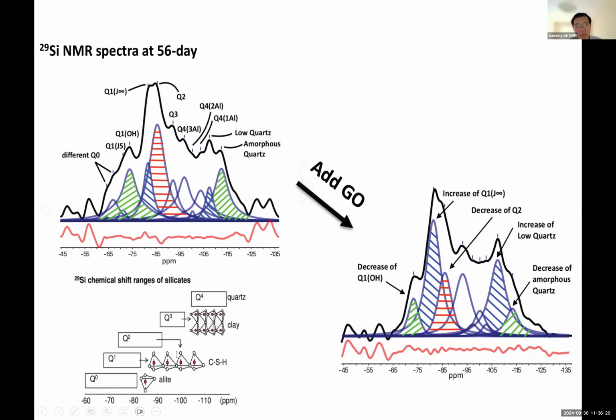But once they have more network structure, more neighbors being silicon or silicate, then you're moving into the domain of Q3, Q4. I would argue that when you have more than 50% Q3, Q4, then it's truly a polymer or geopolymer, instead of a linear polymer, which is a CSH gel or calcium silicate hydrate. I know the cement chemistry is a little bit confusing because here in cement chemistry, C doesn't stand for carbon, it stands for calcium. S stands for silicate, and H stands for hydrate. So it's a little bit different from how we view the chemistry from high school, I guess.